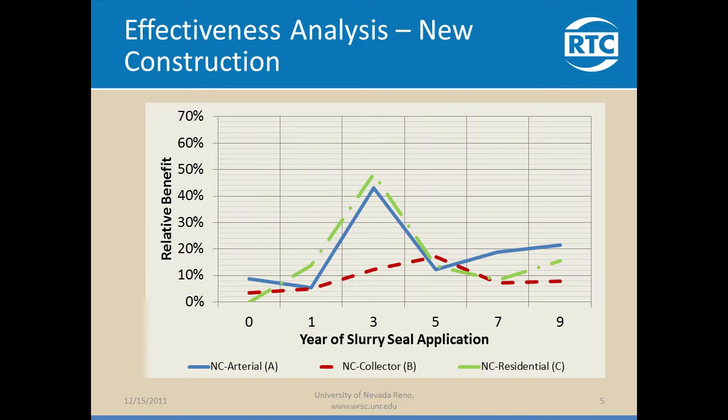It's the glue processes of that. There's an age hardening process that happens. So about year 3, you put that thing down and it starts aging and oxidizing and getting harder and stiffer and actually stronger. And what a surface treatment does is slow down that process. So it retards the aging process of the roadways.